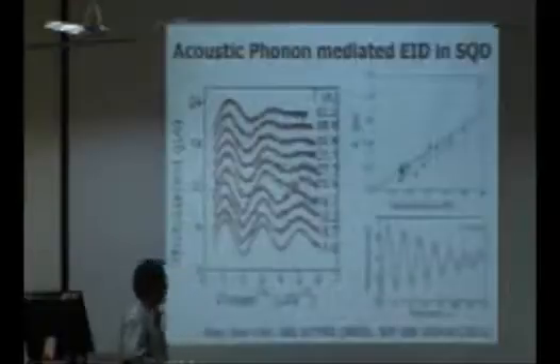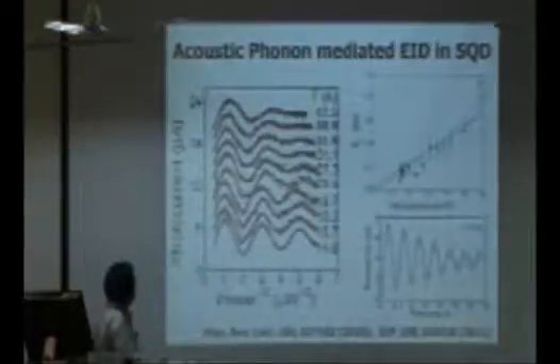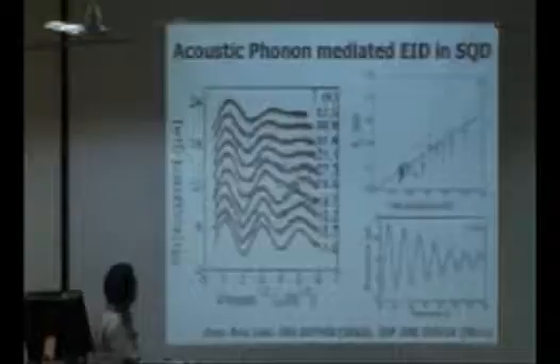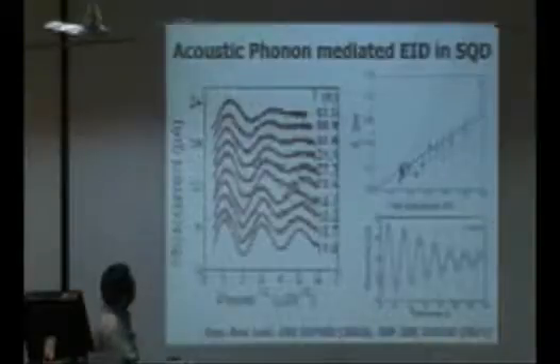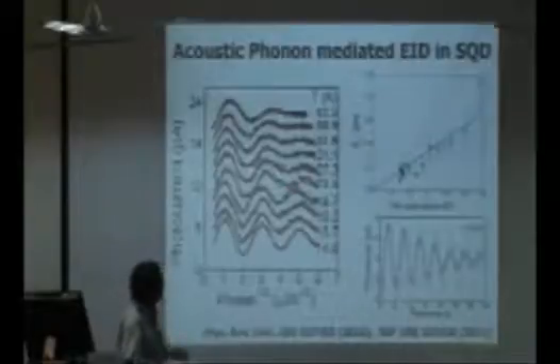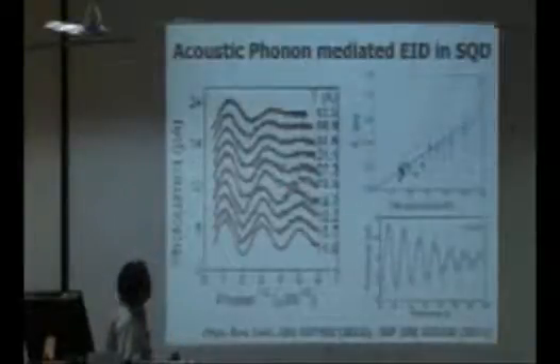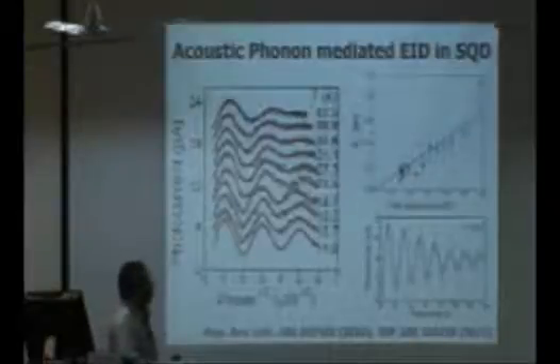Okay. So then, as a function of temperature, we studied the Rabi oscillations in the photocurrent, and then by fitting this to the known theory, we plotted the K2 as a function of temperature, which showed a linear dependence. So this established for the first time that the dominant mechanism for excitation-induced dephasing in single quantum dots is acoustic phonon mediation.